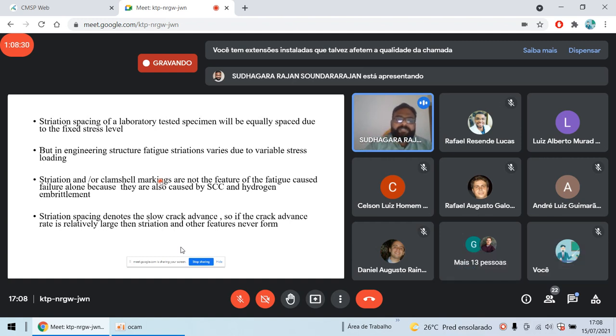The striation spacing denotes the slow crack advance. If the crack advance rate is relatively large, if the material has very little resistance and the crack is advancing very fast, then there won't be any striations. In such cases, the large cracks will be interlinked and ductile failure may occur.